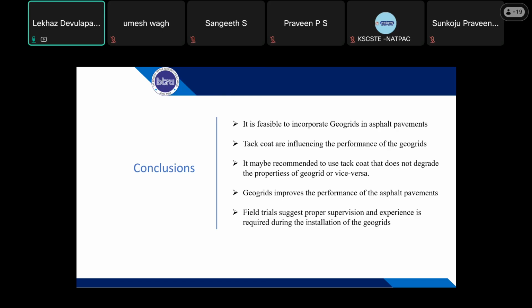The grids are improving the laboratory performance by more than 100 percent, but still we need to keep a cap in the design because the installation damage is there. How we can improve the design, and whether we can improve the life of a pavement or reduce the thickness, will be a conscious decision we need to take from project to project. In the field trial, what we found was that proper supervision is required, the geogrid should be laid in tension, and the undulation should not be there. We required an experienced person to do the installation. Apart from that, there are a lot of challenges when curves come, because laying the roll at the curves is a bit difficult and challenging.